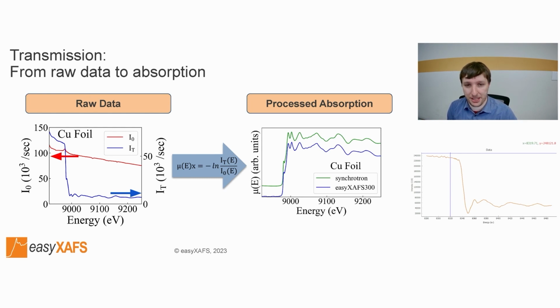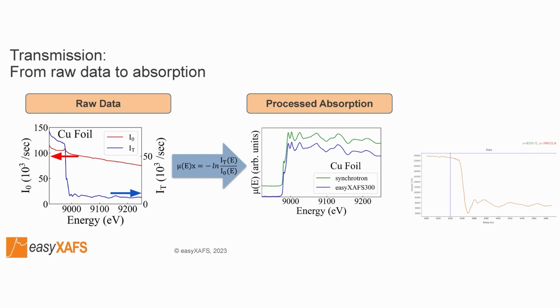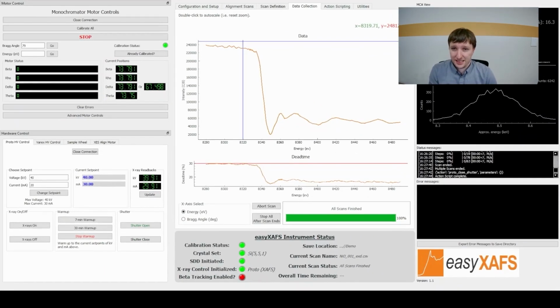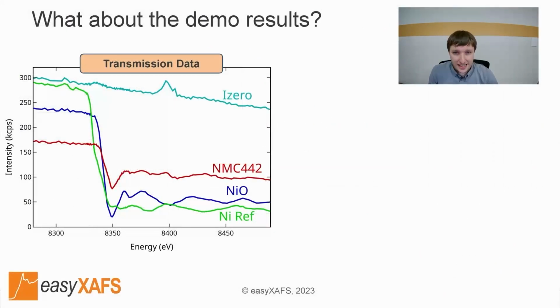The resulting copper K edge absorption data for the laboratory instrument is compared to synchrotron measurements. The laboratory measurements achieve good synchrotron quality energy resolution. Now, as we have been going through these case studies, you have seen the real-time acquisition of rapid XANES measurements on the easyXAFS spectrometer. Here we can now see the transmission data for each of the 3 samples along with the corresponding beam intensity that has been collected as part of the demo measurement.